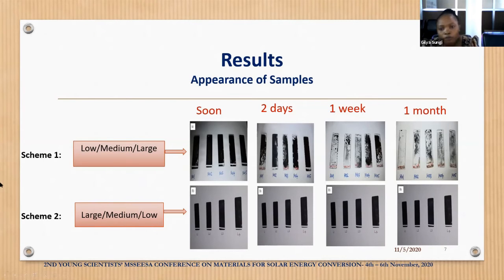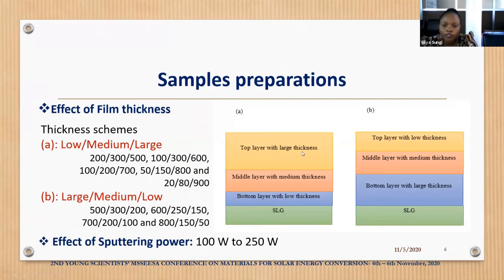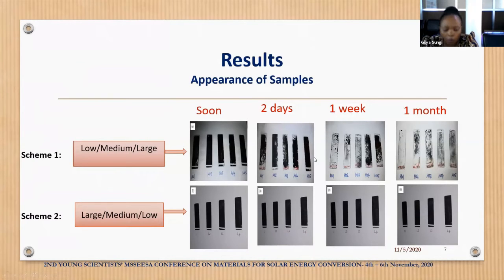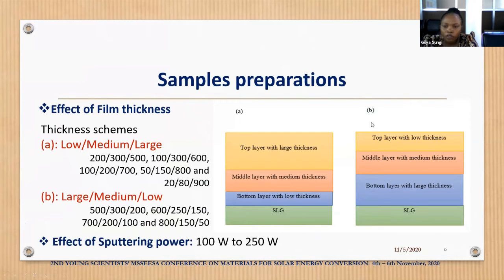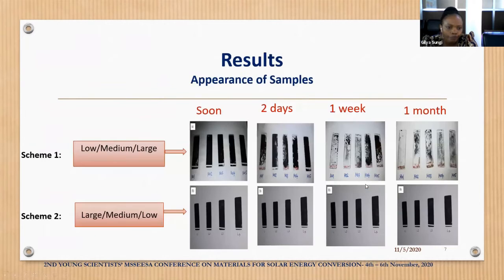And the continuous peeling off is contributed by the variation of working gas pressure. Remember, I said we are going to deposit the top layer and bottom layer at different working gas pressure, whereby we have tensile stress and compressive stress affecting the film, whereby it will affect the film with time. But at large, middle, low, you can see the film didn't peel off with time. This is because the top layer was deposited at lower working gas pressure, while the bottom layer, which is thicker and adhesive to the glass substrate, was deposited at high working gas pressure.